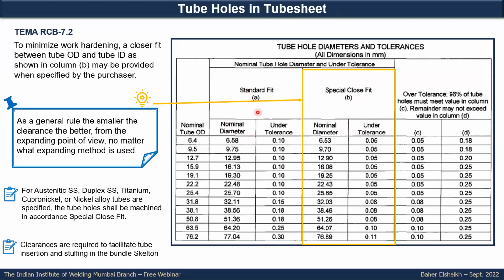Against this, the standard fit with higher clearance is in many cases preferred by the manufacturer because it facilitates the insertion of the tubes during the fabrication work itself. But as long as you don't have a limitation on the material, you can apply standard fit. But the best recommended practice is to apply the special close fit. And here, especially for austenitic stainless steel, duplex stainless steel, and titanium tubes, you need to apply the special close fit clearance.